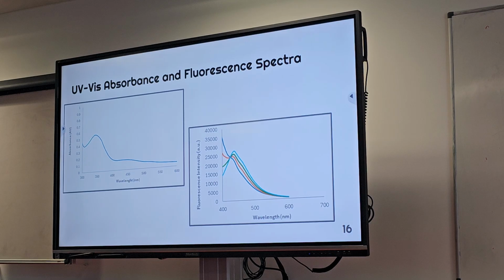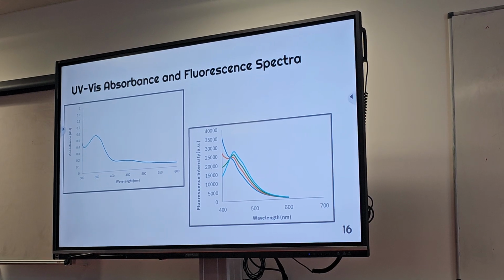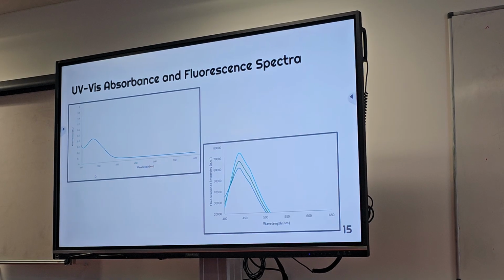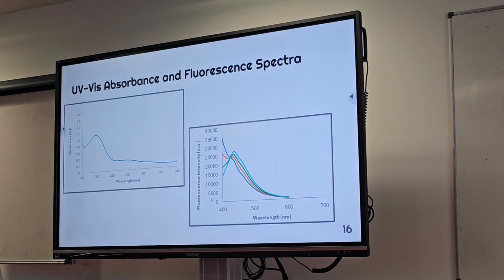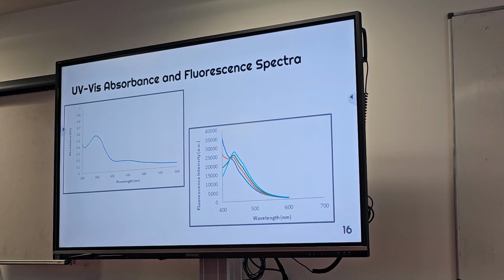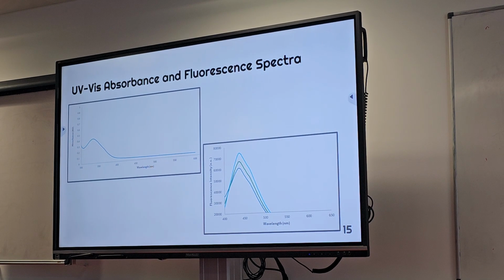For the third method, I didn't use urea and didn't use APTES. I used ethylene diamine for getting more fluorescence. Here you can see that the graph for absorbance is the same, 300 to 350, like the urea one. And here the fluorescence intensity is good. It's consistent when exciting at different wavelengths from 320, 330, 340, and 350. Maybe the size is good in this one, but the fluorescence intensity is lower compared to the second method where I used urea.